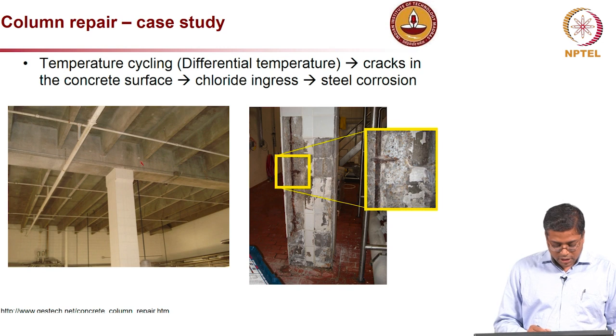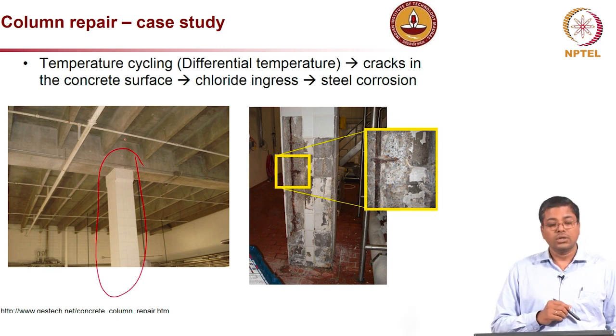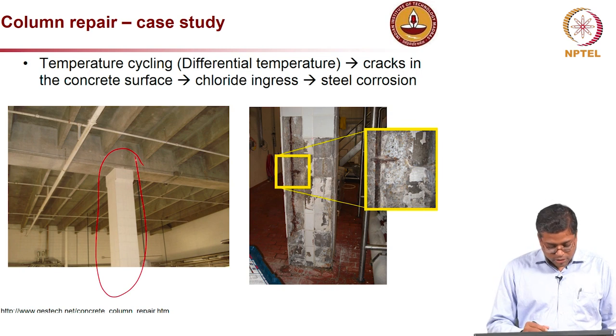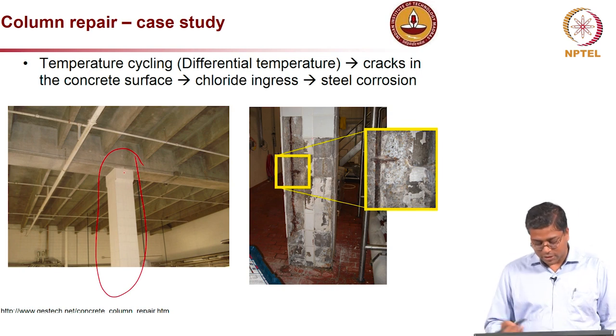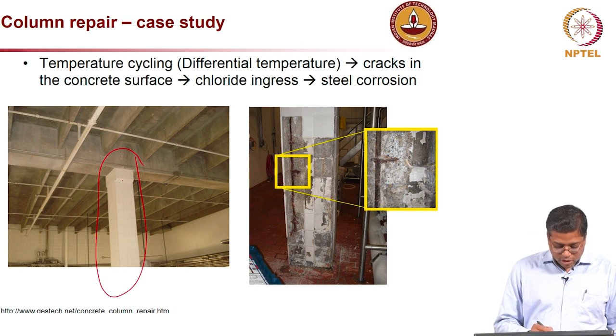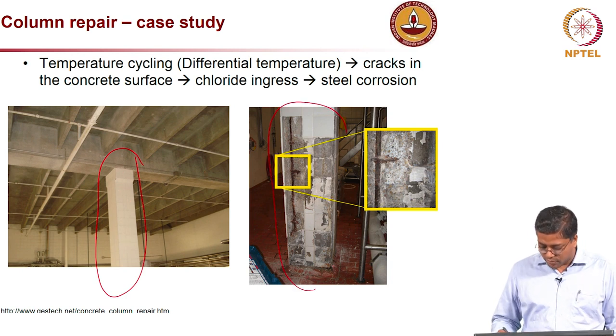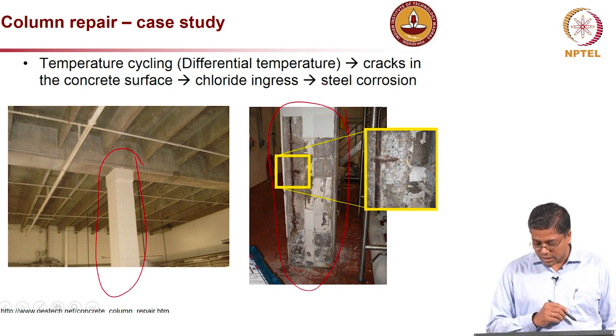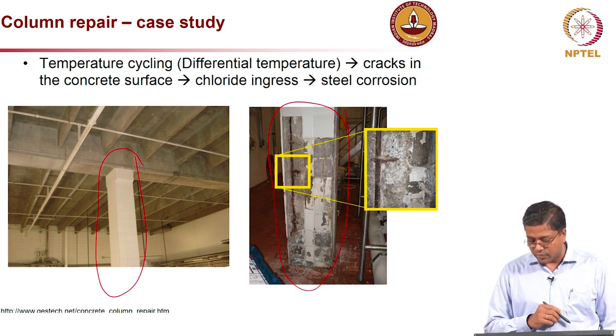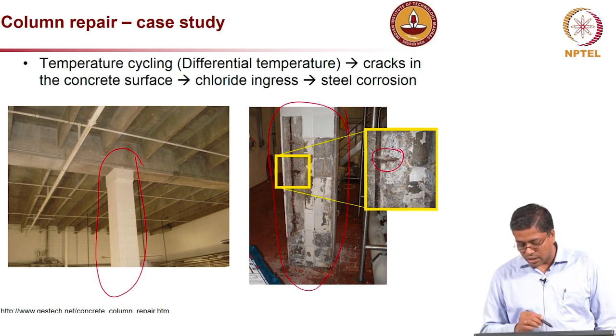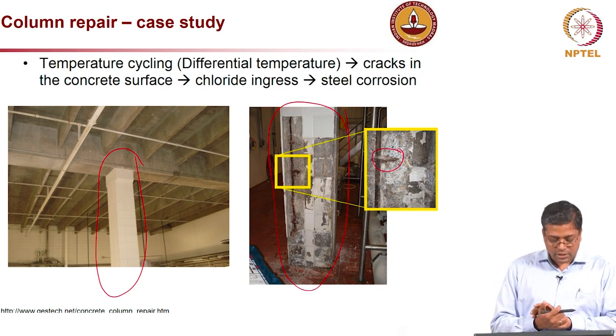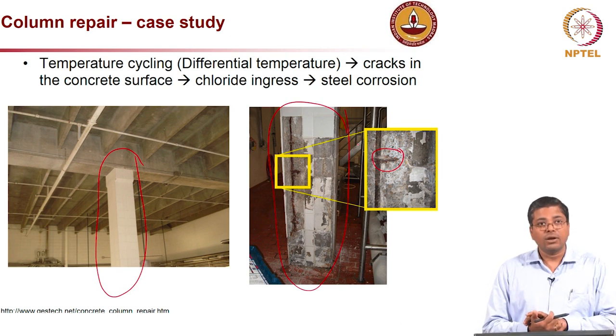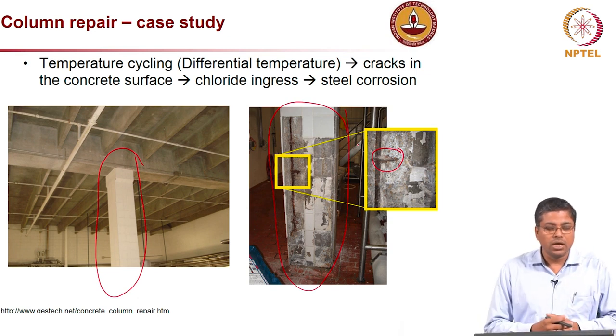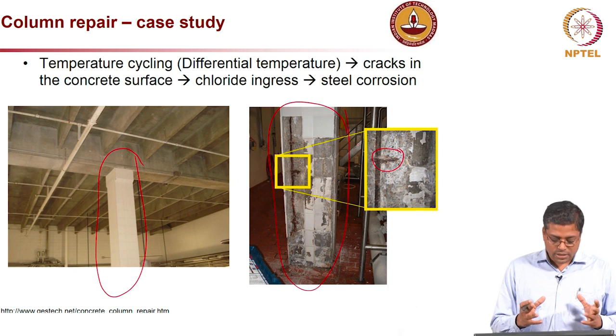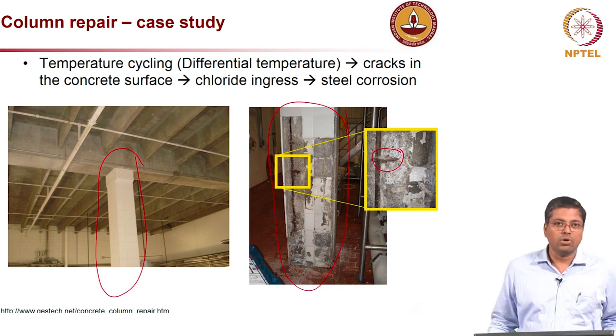You can see the picture here, which is, sorry, not after repair, this is before repair itself. You can see the top of the column is good, but at the bottom of the column, this is how the situation was. You can see significant corrosion, which led to delamination. In this particular case, this was a factory, a chemical plant, where there was significant variation in the temperature, and at the same time the ambient environment had a significant amount of chlorides.